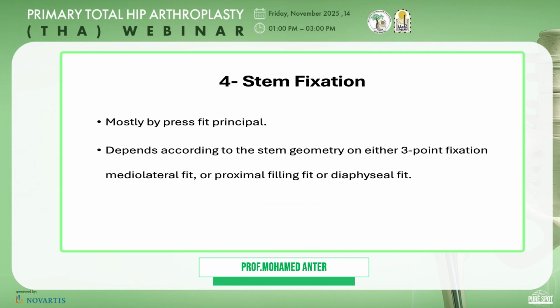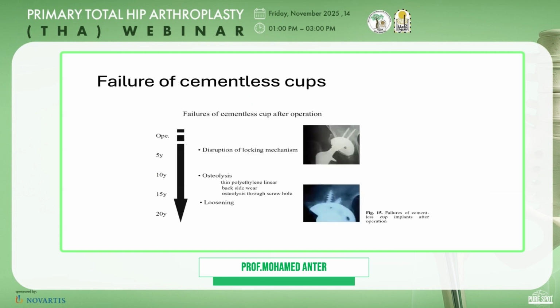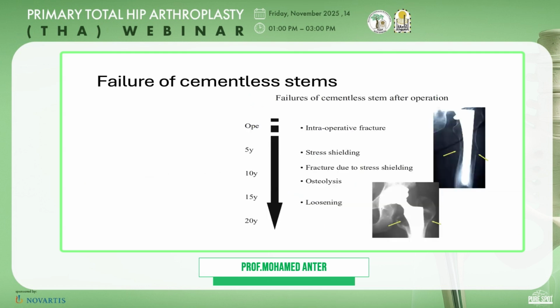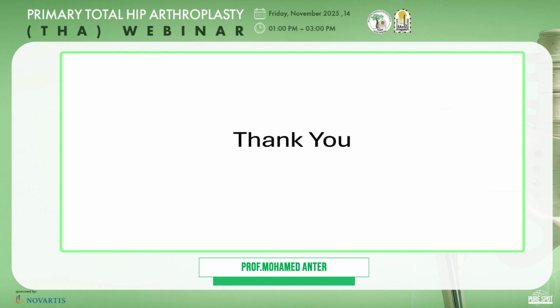Surface coating is the same as the cups, and for the stem fixation, mostly for the stem, we are using the press fit principle. Failure of the cementless cup is due to either disruption of the locking mechanism, osteolysis, or loosening, and for the stems, either intraoperative fracture, stress shielding, osteolysis, or loosening.